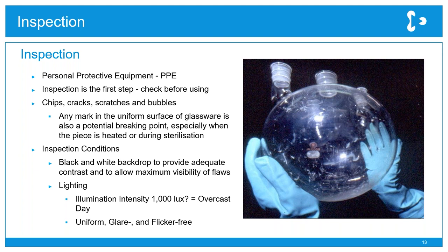And all research labs should have cut and puncture-resistant gloves like Kevlar or D-Flex, and an approved sharps disposal container large enough to contain broken glass. Inspection is the first step before working with any piece of glass. In addition to the dimensional inspection, quality inspectors check for chips, cracks, and blisters. One thing that's important when inspecting is lighting. So usually you require 1,000 lux, and this alongside a black and white backdrop can really help to improve the visibility when inspecting the glass.